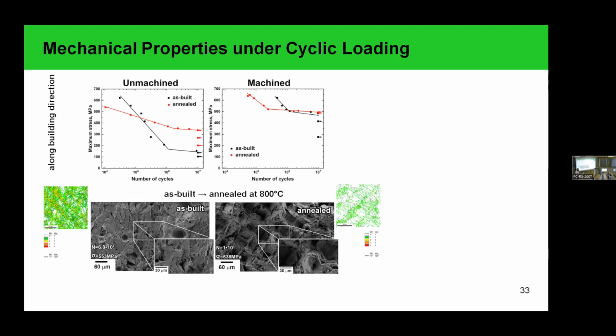Analyzing the fracture surface of these specimens, we see that for the as-built materials, the fracture surface demonstrates brittle fracture, and for the annealed materials, ductile behavior is observed, which is associated with the removal of residual stress.